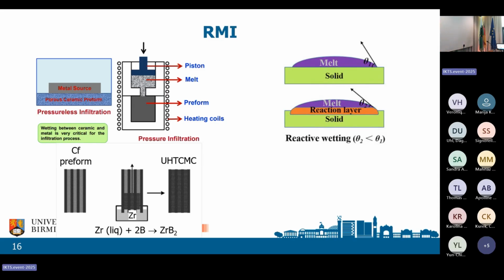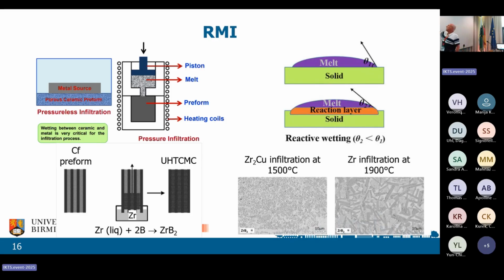But here we're talking of the ultra high temperature, so we're using molten zirconium. Not the easiest material to handle. Then you also put some boron-based powder, something that will give you your source of boron, and you rely on the reaction as the melt progresses up the preform. You've got that reaction happening inside it. It takes about 1900 degrees centigrade to get that to work with pure zirconium. That's a high temperature. The fibers don't like that temperature, and you get a coarse microstructure.